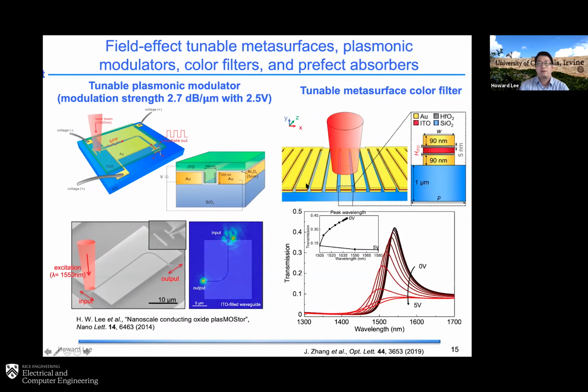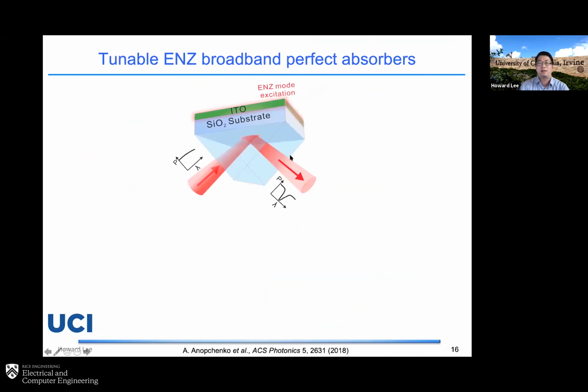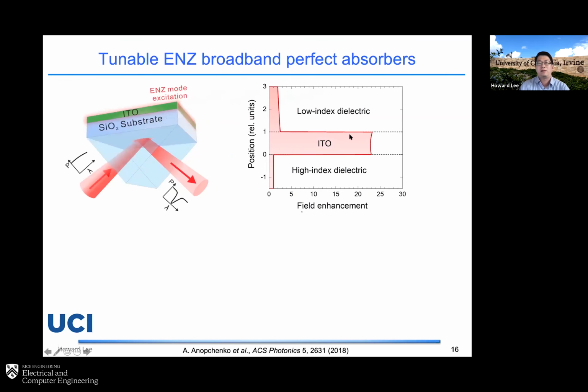But as I mentioned, we're focusing here more on the ENZ property. To look at the ENZ property of the TCO material is quite simple if you want to excite this ENZ mode. Basically, you can just have an ITO film here, and excite it at a certain angle with the prism. Then with a certain phase matching condition, you can excite this ENZ mode. Once you're able to excite this ENZ mode, you find that you can have really high field confinement. The field can enhance significantly on this ENZ material, so you can see a really strong enhancement of the electric field here.